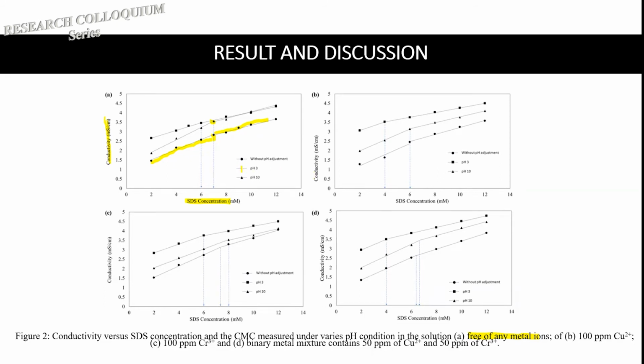You may realize that at lower pH, for example pH 3, the CMC is lower, at around 6 millimolar. Without pH adjustment, which is around pH 5 to 6, the CMC is around 7 millimolar. This is the case for blank water only. But if we put in 100 ppm of copper cations, what will happen? We observe that the CMC value is further reduced. For example, at pH 3, the CMC is around 4 millimolar, compared to the 6 millimolar over here. On the other hand, without any pH adjustment and at pH 10, it is 6 millimolar compared to the 7 millimolar. So this is the case for the Cu.